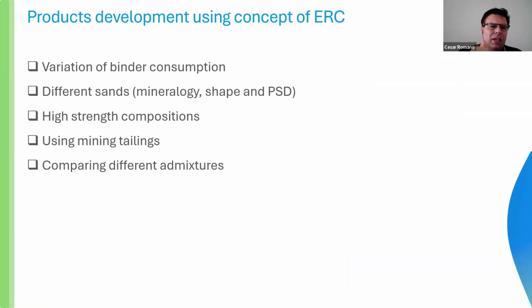So we applied this concept of extended rheological characterization in many of the compositions we developed in the lab. We evaluated the variation of binder consumption, different sands, to evaluate the mineralogy, the shape, and the particle size distribution. We developed the high strength composition, but for high strength composition, we needed to increase the cement consumption in the composition.